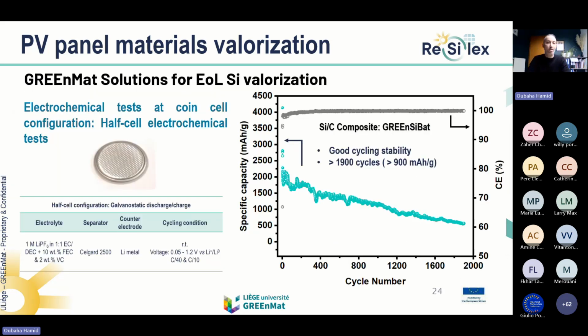Then we evaluated this material in lithium-ion batteries in half cell configuration using commercially available electrolytes and commercial separator, and lithium metal as a counter electrode. You can see here that our composite, which is now called GREEnSiBat, has good cycling stability, and up to more than 1,900 cycles, we can still deliver more than 900 milliampere hour per gram.